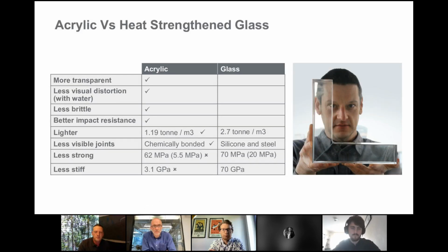watertightness. So if we look very briefly at the properties of acrylic versus heat strengthened glass, acrylic is more transparent, as we said. There's less visual distortion with water because its refractive index is more similar to water, which is why it's used in aquaria, whereas glass, you get an awful lot of distortion when you look between air, glass, and water. As a material, it's plastic, so it is much less brittle than glass.